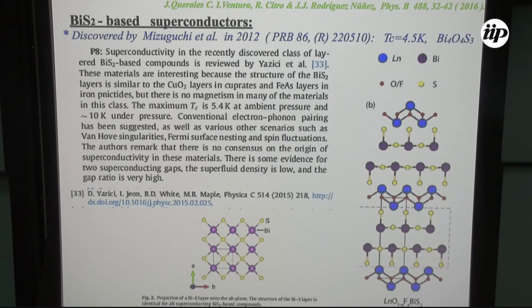So let us very quickly mention, this is, for example, the kind of crystal structure you find in these compounds. And this is a paper by Mizuguchi where they first found the critical temperature of 4.5 Kelvin. It was actually in this compound.